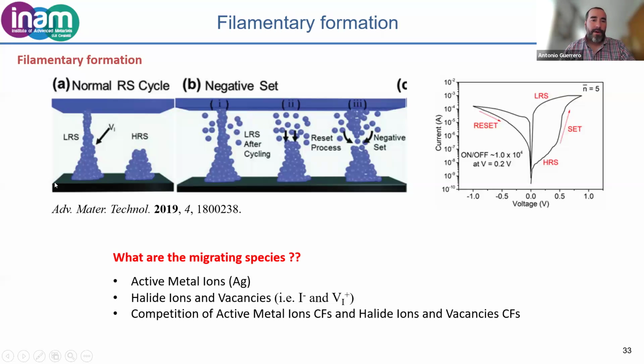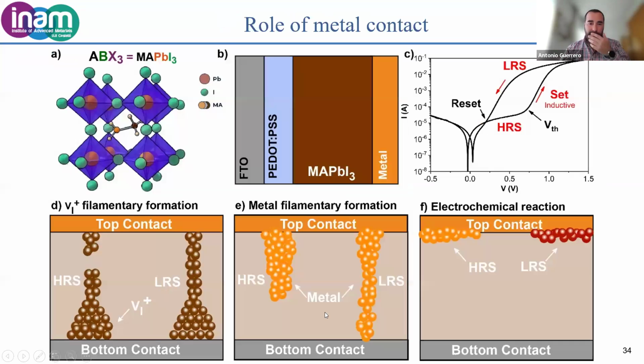The main activation mechanism, which is believed at the moment, 4 years later, is connected to filamentary formation in the device. So let's say, for example, that we have a contact which can migrate, for example, silver, and can form a filament of something conductive. It could be the low resistive state, and if we can modify the position of the ions by having an electrical field, we could change from low resistive state to highly resistive state. But what we've been trying to understand over the last few years is what is actually migrating inside the perovskite. Are the active metals like silver? Are the halide ions and vacancies? Is there a competition between the two different methods?